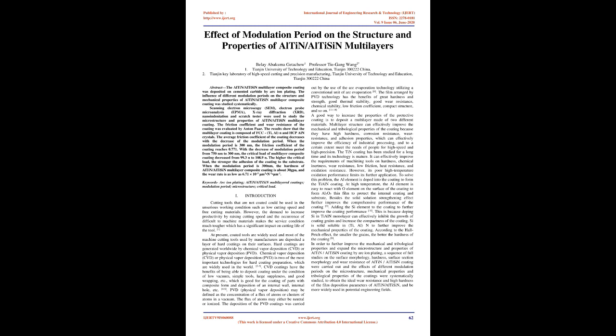Introduction. Uncoated cutting tools could be used in less severe working conditions such as low cutting speed and free cutting materials. However, the demand to increase productivity by raising cutting speed and the occurrence of difficult-to-machine materials make the service condition much tougher, which has a significant impact on the cutting life of the tool. At present, coated tools are widely used, and most of the machine cutting tools used by manufacturers are deposited with a layer of hard coatings on their surfaces.